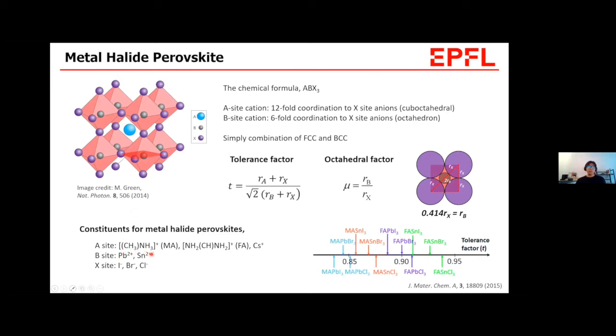Mostly lead ions or tin ions are used, and in this X site, the iodide, bromide, and chloride halides are used. Empirically, material compositions with this tolerance factor between 0.8 and 1 are found to be able to be perovskite at room temperature.